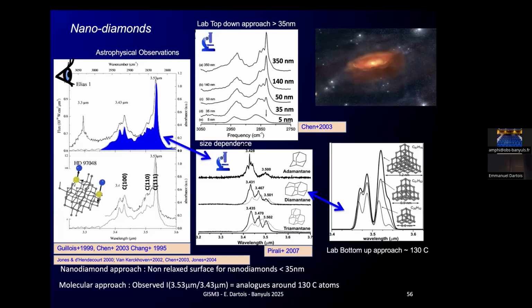There have been several approaches from the lab point of view: the top-down approach to the formation of this, where you take nanodiamonds, decrease the size and look at the spectra; and the bottom-up approach, looking at diamondoid molecules and increasing their size to reproduce the spectra and calculations. Typically, the ratio of the bands you observe from the calculation tells you that you have around 130 carbon atoms in these observations.